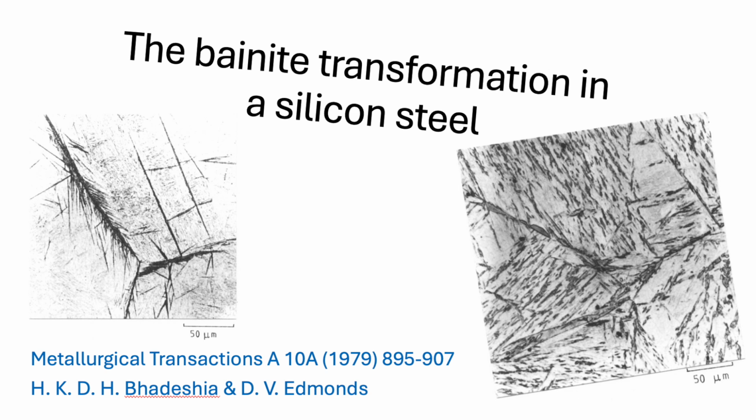Okay, let's start with the kinetics. The timing of the transformation. We usually talk about upper bainite and lower bainite formed at different temperatures. Right, that's the classical distinction based on how it looks, the morphology. But the first kinetic clue here was something called the incomplete reaction phenomenon. Incomplete, meaning it just stops. Pretty much. The bainite transformation often just peters out, even if you hold the steel at temperature for a really, really long time. The paper mentions like 32 hours at 452 Celsius. Wow, 32 hours and it's still not done? Nope, it stops, leaving behind a fair bit of the original phase, austenite, untransformed. We call that retained austenite.